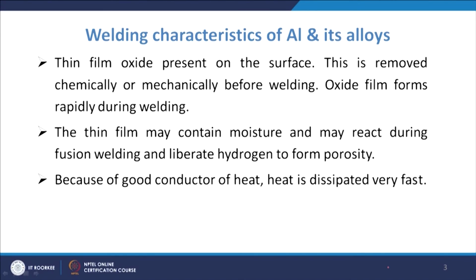So, that is basically becoming a challenging job when you are doing the welding of aluminum. What is happening is that this thin film which is formed may contain moisture, and it may react during the fusion welding and liberate hydrogen to form porosities. That is the main challenge: the film may contain moisture, and once it interacts with the heat, there is a chance of liberation of hydrogen, and that will form porosities.